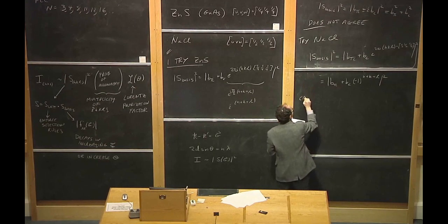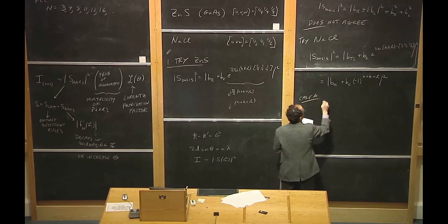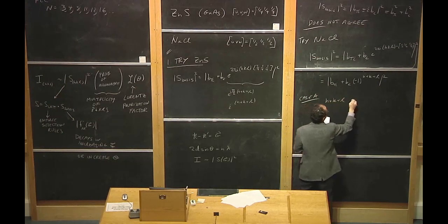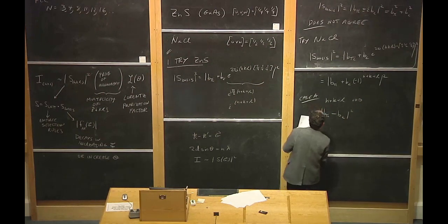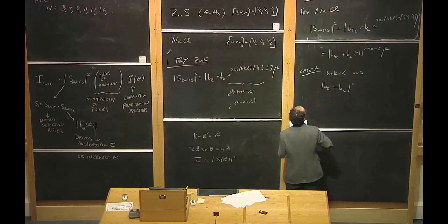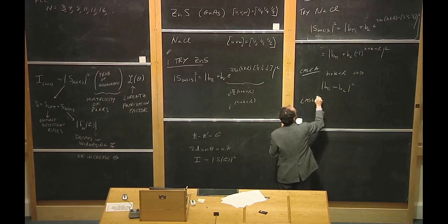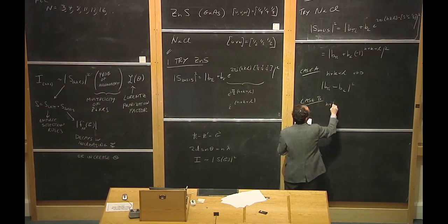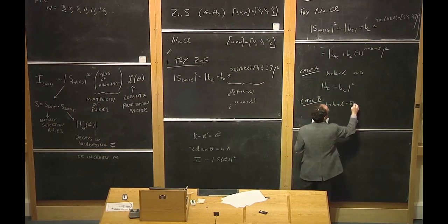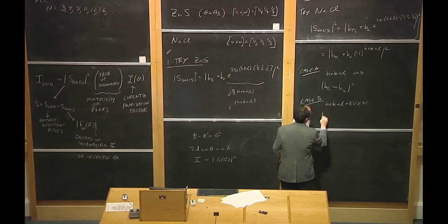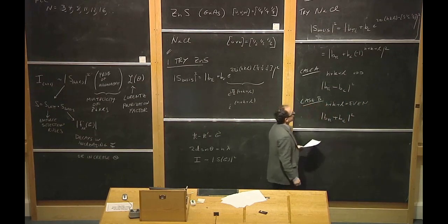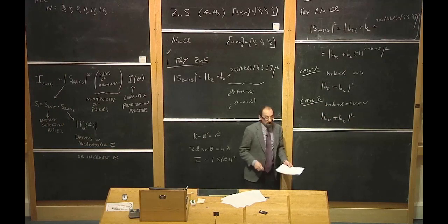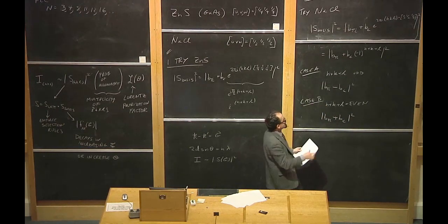So there's two cases we can have. Case A is H plus K plus L is odd, in which case we have B titanium minus B carbon squared is the answer. Whereas case B is H plus K plus L is even, in which case we have B titanium plus B carbon squared. Okay, so now which one is largest here?